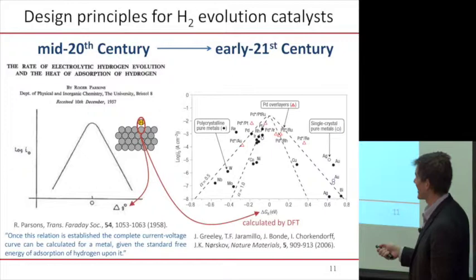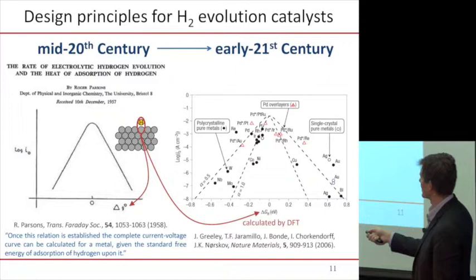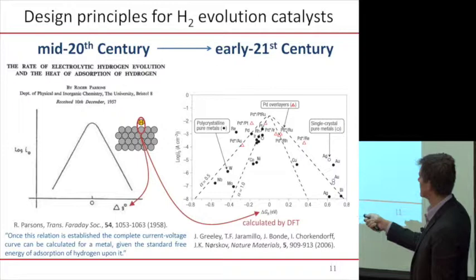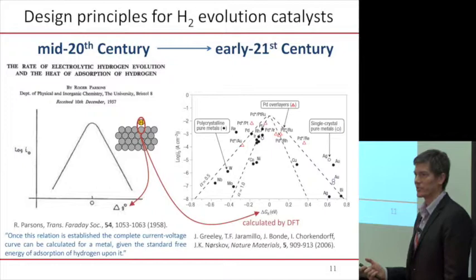And if that thought occurred to you, congratulations, that thought occurred to Roger Parsons over 50 years ago as he was doing paper and pencil theory, and basically showed this is an activity plot. He says that if you look at this hydrogen atom sitting on the surface, the delta G of that hydrogen sticking on there, the best catalyst is at the peak here where that delta G is close to zero. Not too strong, not too weak. So that really helped formulate conceptually what the problem is.